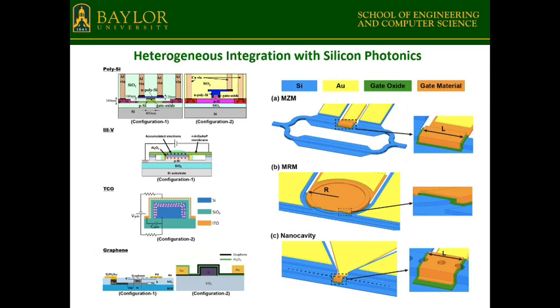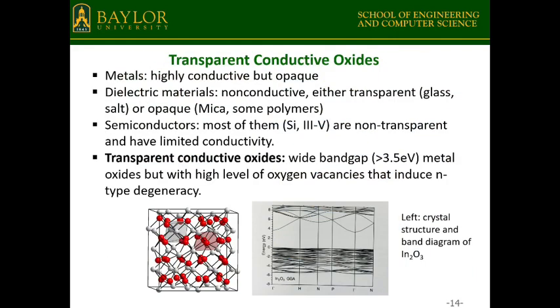Okay, so some work has been done before. You can put polysilicon, III-V material like indium gallium arsenide, the transparent conductive oxide, and the graphene on top of the silicon. And also you can have different choices of the devices. Due to the time limit, I'm not going into the details. But I want to emphasize the material here. So we use transparent conductive oxide.